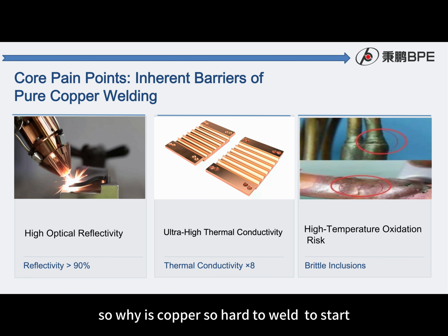So why is copper so hard to weld? To start, at room temperature, pure copper reflects over 90% of standard infrared laser light, meaning the energy just bounces off. On top of that, copper moves heat 8 times faster than steel, making keyhole stability a nightmare as heat dissipates instantly. Finally, liquid copper oxidizes in a heartbeat, creating brittle joints that ruin conductivity.